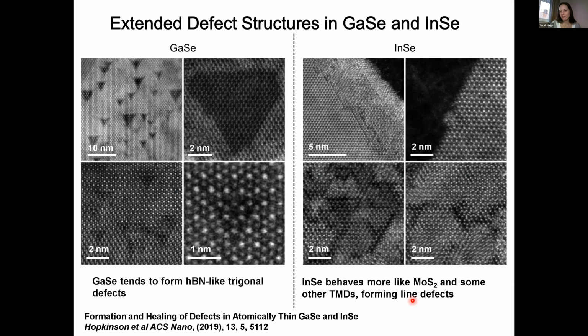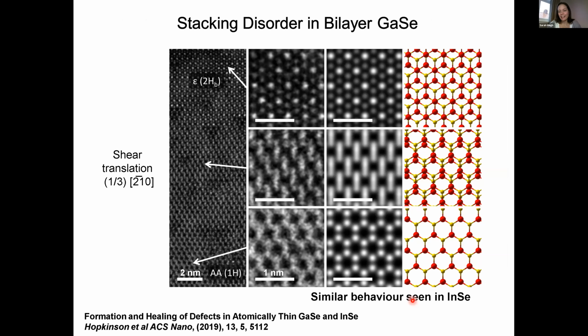But I would say that this is really not fully understood: why these two isostructural materials are behaving quite differently in terms of their extended defect properties. We see that both have differences in stacking. I'm just illustrating it here for gallium selenide. We get this 2H type stacking, and that goes off transitions to an AA type stacking.